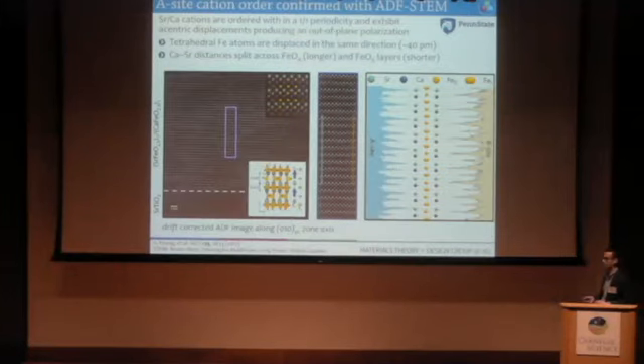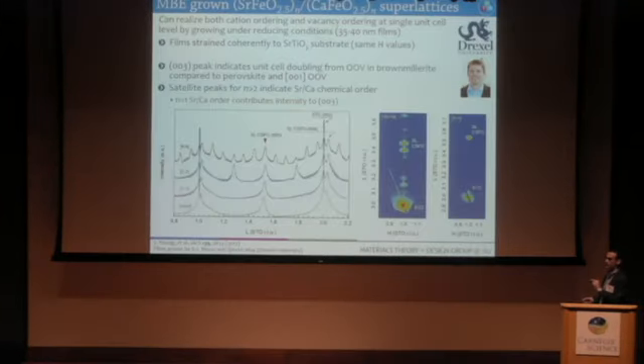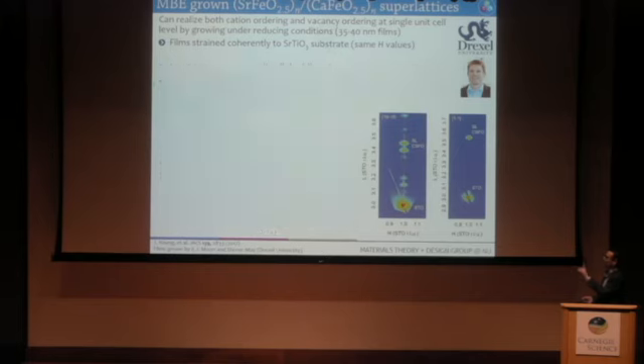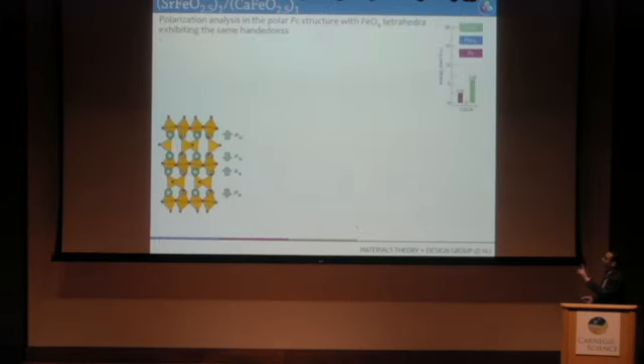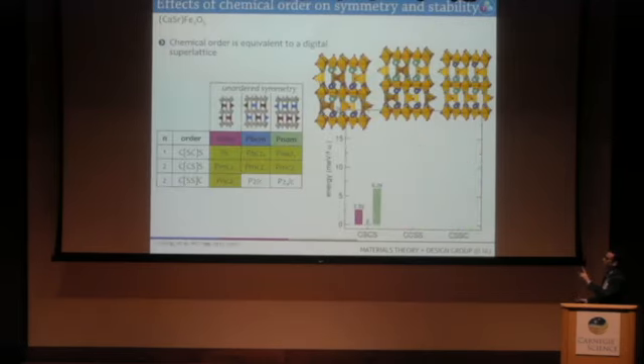Yeah. It looks like you're talking about polarization along the chains, right? So in the monoclinic structure, you have an in-plane polarization and an out-of-plane polarization. In the other two structures, it's always orthogonal this way. Right, but as soon as you put the cation ordering in the vertical direction, like in the first of the three, this lifts the mirror plane this way that allows a polarization in that direction. Okay, so in that case, the polarization is in the layering direction. Right, because the chains are still 50% left and right, so they cancel. Okay, so that one looks hard to switch.